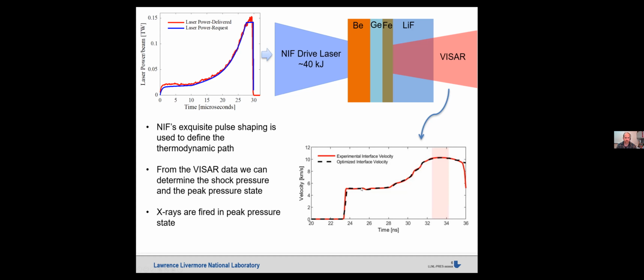So we measure, again, we get a very steady shock wave. So this shock wave is steady at the few percent level, which is a sort of a testament to the capabilities of the NIF for pulse shaping. And then we get this shockless compression wave and this nice long hold at the peak pressure state. And so then this shadowed region is shown where we're taking X-ray diffraction.